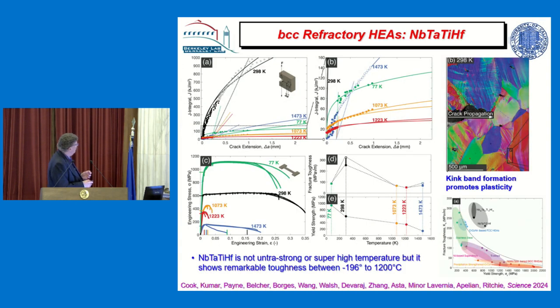We have managed to generate an alloy now, which is called niobium, tantalum, titanium, hafnium. I think it's going to appear in Science this week, but this has very, very good toughness, very strange for that reason. It doesn't have any strain hardening like the other systems I showed you, very different, but it generates something called kink bands, which Orowan, one of the people who invented the dislocation, suggested about 70 years ago, that kink bands could be interesting.